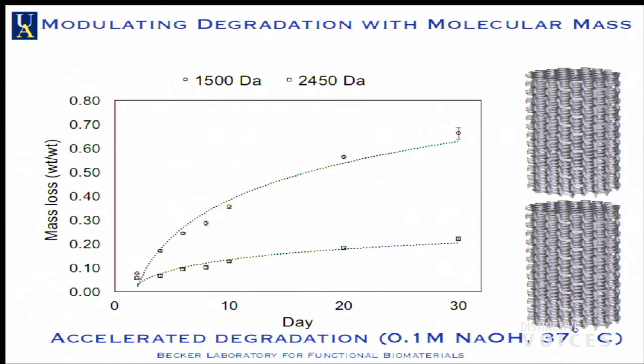Here we have two different materials, same structures. This is the fine structure. Here we have 2450 Daltons, so a little bit longer chain, more cross-links per unit chain length. And you can see that the lower molecular weight, again, degrades much faster than the one that's higher cross-linked.